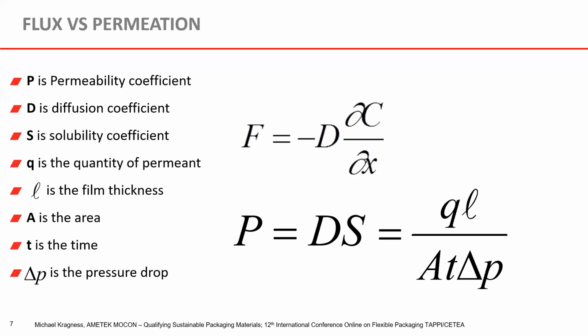So you see, if you're talking about permeation, you have to take into account the thickness of the medium that you're permeating. That's the main difference between permeation and flux: you normalize for the thickness of the medium. If you were looking at different barrier structures in some book or literature, it will always have the permeation rate, because that gives you the best apples to apples comparison between barriers, because it's normalized usually to a 1 mil thickness or a 1 centimeter thickness. So it gives you a good gauge of what is a better barrier.